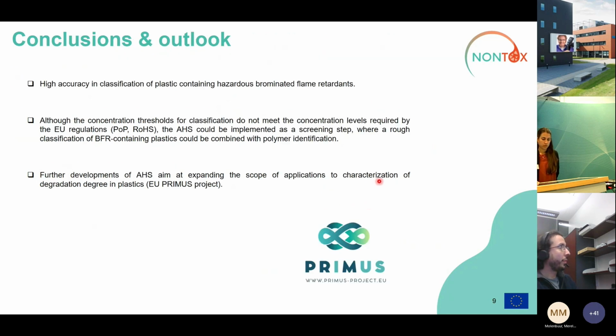So to conclude, we showed high accuracy in classification of plastic containing hazardous brominated flame retardants, in addition to the classification of the polymer content itself. And although the concentration thresholds that we use to classify are higher than the levels required by the regulations, the AHS could still be implemented in a screening step where you can use this classification in combination with the polymer identification as well, to separate very high fractions from the lower fractions.